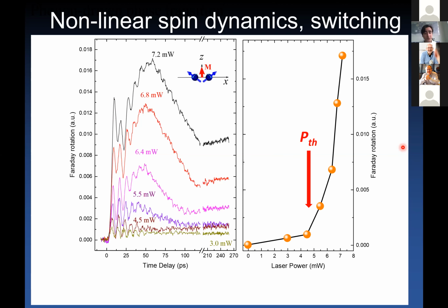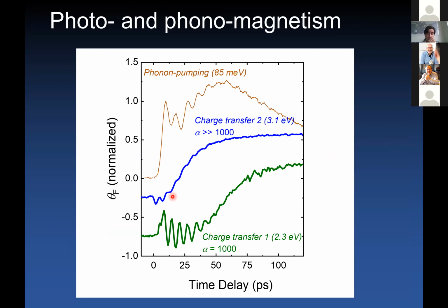Okay, so this data indicates that we indeed have nonlinear spin dynamics with switching from the antiferromagnetic phase to the weak ferromagnetic phase. This type of transition can also be induced by charge excitation. So this has been demonstrated in the past, but there is a key difference.